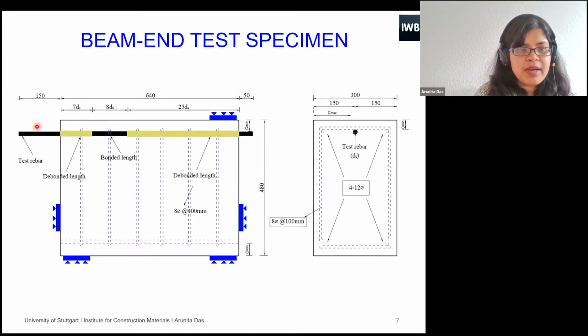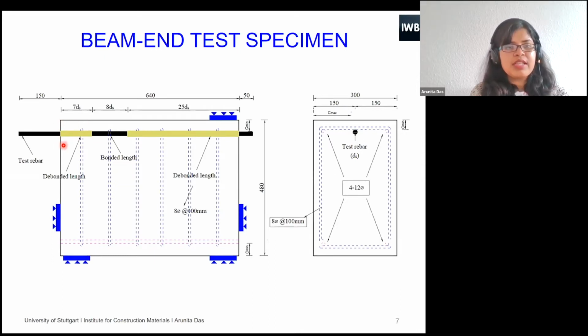So this is my test rebar, and this is the bonded length, which is considered as 8 times the diameter of the rebar for all the numerical investigations. There is an unbonded or debonded length, initially a debonded length of 7 times the diameter, which is provided intentionally just to prevent a concrete cone failure of the structure. Then these are the stirrups, which are given exactly in the middle of the bonded length, with a spacing of 100 millimeter from each side.